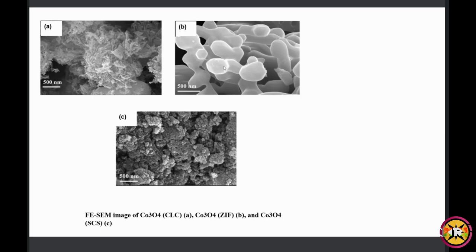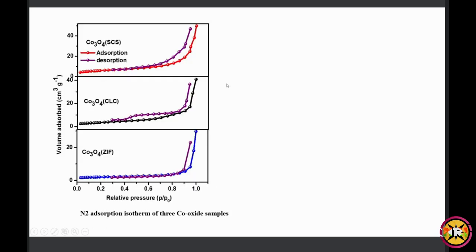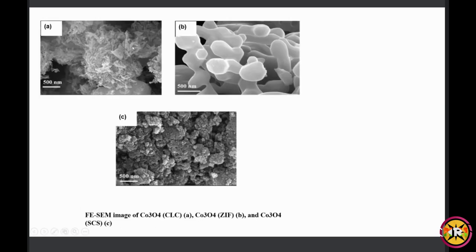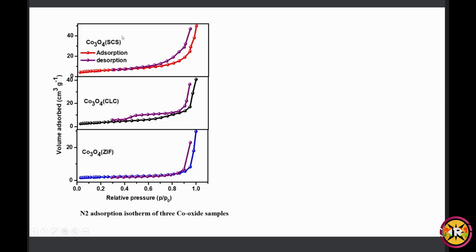So from here also, the particle size of Co3O4 SCS is half of the other two. So from here we can conclude that as the particle size of Co3O4 SCS is less than the other two, and it is nanostructured, the surface area will also be high for Co3O4 SCS. So to cross-check this, I have done N2 adsorption-desorption, and what I have observed is that for Co3O4 SCS, the BET surface area and pore size are also higher than the other two.